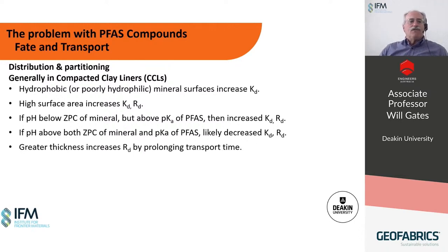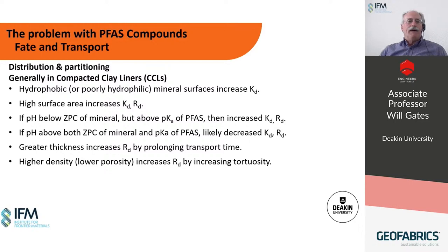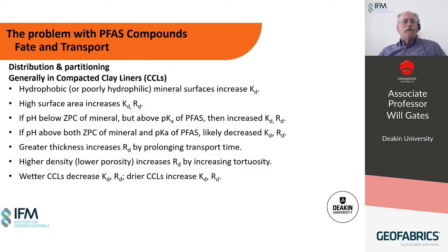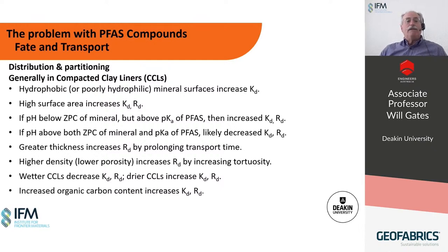We can expect that the actual thickness of the liner itself is going to be very important for prolonging transport time, and this is just by virtue of the fact that we have a large amount of tortuosity. That's very much also related to the density and lower porosity of the lining system. Wetter lining systems will probably result in a decrease in the partitioning to the mineral surface and an increase in the partitioning of the PFAS into the water column. For drier materials, we can expect the opposite, but the jury's still out because we don't have enough information on that yet. The presence of organic carbon in the mineral systems is very important. And I guess basically a thick, highly compacted, low porosity lining system with a high amount of variable charge minerals, including organic carbon, is going to be an ideal situation for PFAS adsorption.